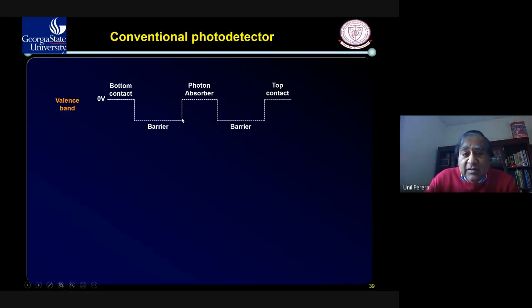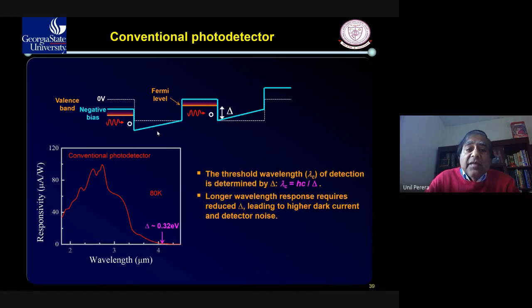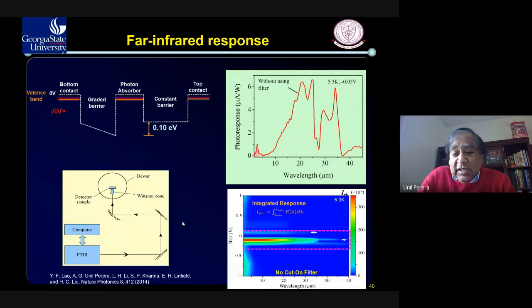So the standard detector was something like this, p-type, the emitter and barrier. So this is what we were expecting the result. So when we apply bias and send light, we get carriers through and get this response. But one of my students, who was another postdoc afterwards, I asked him to come up with a model to improve the performance. So he came up with a model saying we need to have a graded barrier and an offset. So this is the offset, this is the graded barrier, and this is what we saw when we did this measurement. This is the expected result, 3 micron around that, but this is the result we got, which is very long wavelength. So you can see the image here.